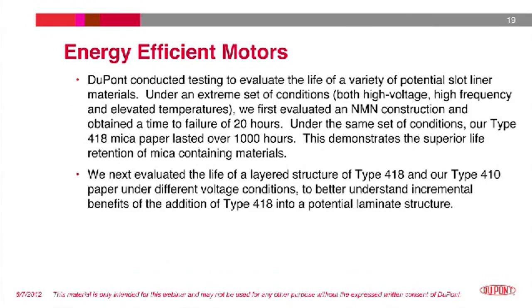Using sinusoidal voltage endurance testing, we first looked at a typical NMN laminate under a combination of corona and elevated temperatures. The testing was conducted at 360 Hz to increase the effect and obtain results in a shorter time. For the test conditions selected, the NMN lasted around 20 hours. We then evaluated using our Type 418 mica containing aramid paper under the same test conditions and obtained a lifetime of 1,000 hours.